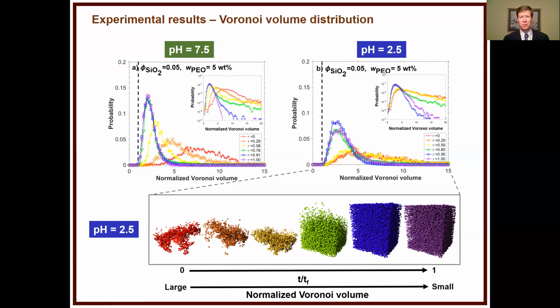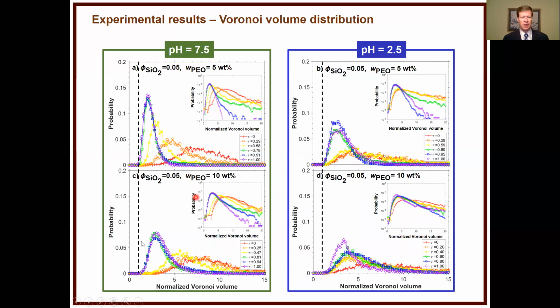So how does this relate to pharmaceutical processes? It actually can relate quite a bit. So just to finish off the data here, at 10 weight percent, you can see that we don't have as drastic of changes, and we end up with a much more open microstructure.